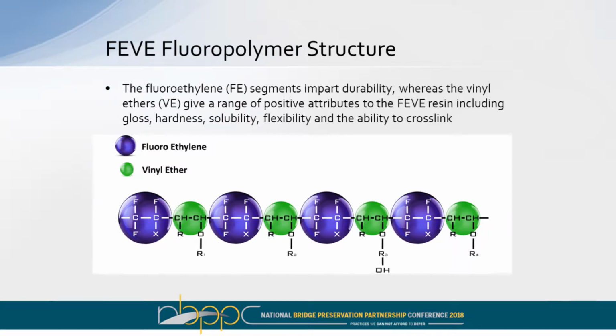The vinyl ether allows us to put functional groups on it to make it soluble in solvents and to make it reactive. So most people who are using these materials are making fluorinated polyurethanes. The chemistry is no different than a polyurethane chemistry. The life of the material, though, is much longer.